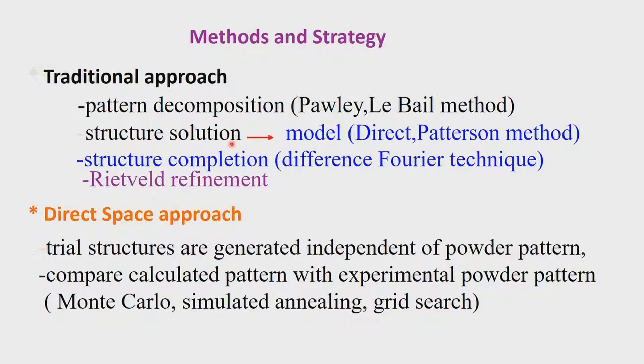The structure solution — we can develop a model either from direct methods or from Patterson methods, and that can be taken to structure completion by the difference Fourier technique. Then we put the structure in and do the Rietveld refinement, refining the profile first, taking it to the final possible refined values of Rp and Rwp, and then introducing the structural parameters xyz, etc. It is not a straightforward procedure like in a single crystal, where you just press a button and the least squares refinement is done. Here we have to release the parameters in a specific way because we are dealing with very subtle things.